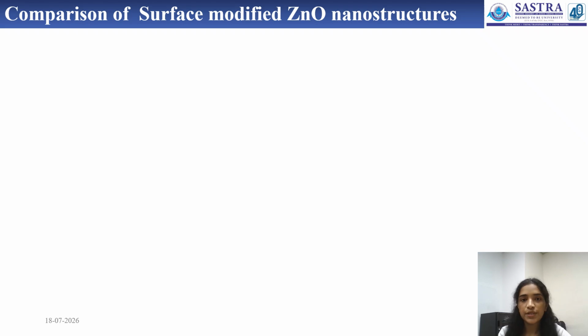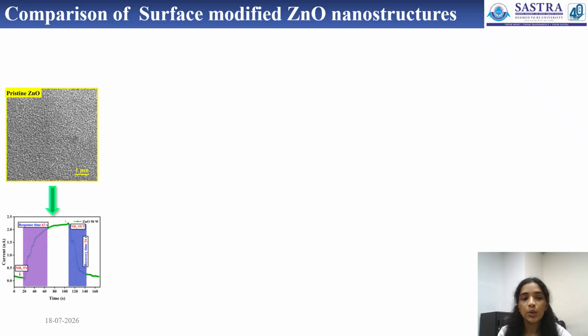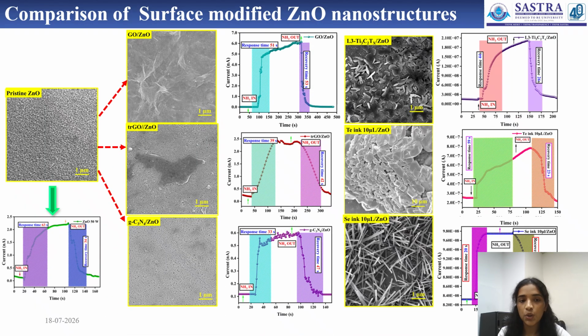Moving to the comparison of surface modified zinc oxide nanostructures, the pristine zinc oxide exhibits nanograin morphology with response and recovery times of 63 and 34 seconds for 10 ppm of ammonia. And the surface modification of pristine zinc oxide using graphene oxide, reduced graphene oxide, graphitic carbon nitride, MXenes, tellurium, and selenium. These FESEM images show the distinct morphological changes after each modification, while the sensing graphs demonstrate the improved response and recovery times. Among these samples, the MXene decorated zinc oxide shows shorter response and recovery times of 39 seconds and 42 seconds for 10 ppm of ammonia.